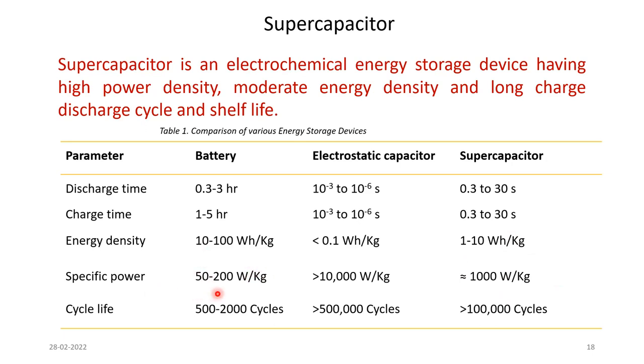And cycle life is another very great advantage of supercapacitors. This means a supercapacitor can be charged or discharged up to 1 lakh or more times; the charging-discharging process is possible on the supercapacitor electrode. But in the case of a battery, it is very limited, to 500 to 2000 cycles. And in the electrostatic capacitor, there may be 5 lakh charging-discharging cycles.